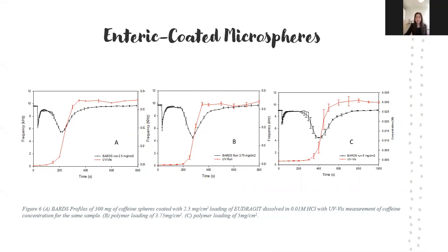So what is the lag time phase? The lag time is the BARDS response to the polymer coating erosion, and it's represented in a BARDS spectrogram by this kind of flat line that you see here. And that's purely the outer coating, that functional polymer coating, eroding in the media provided.